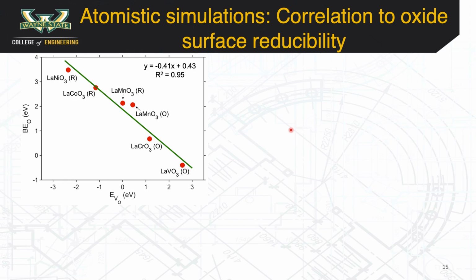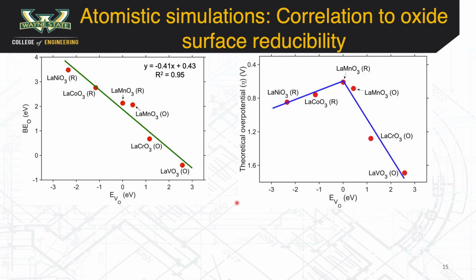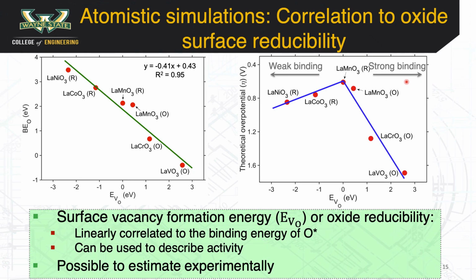What is also interesting is the binding energy of oxygen scales linearly with the oxygen vacancy formation energy, which describes the oxide surface reducibility. This suggests that one can then use the surface oxygen vacancy formation energy to describe the electrocatalytic performance. The negative nature of the slope in this case inverts the weak binding and the strong binding legs. Oxides on the left leg are now limited by weak binding, while oxides on the right leg are limited by strong binding of oxygenated intermediates.